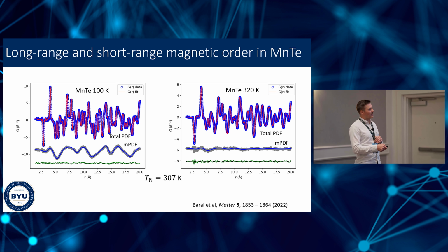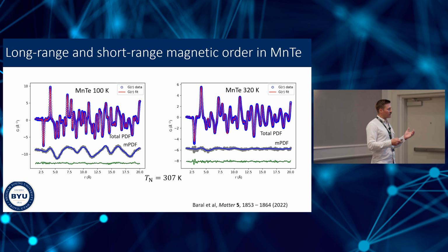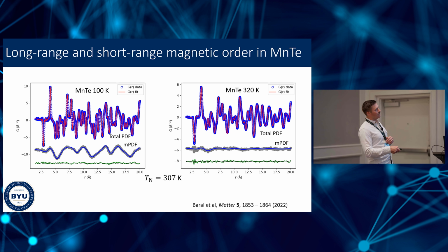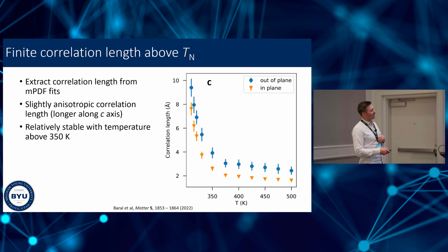So by collecting magnetic PDF data at many different temperatures, we can look at the evolution of these short-range magnetic correlations. We can pull out the correlation length, for example. So here's the correlation length in the plane as well as out of the plane at various temperatures, which we extracted from our magnetic PDF fits.